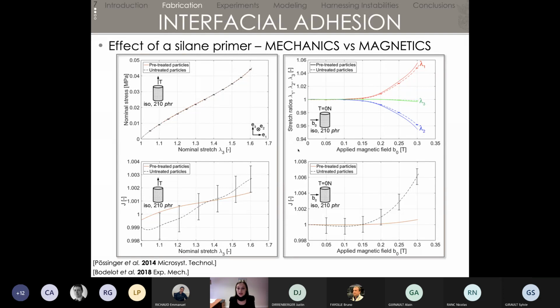And then on the right, the sample which has been pre-treated keeps its J around 1, and the one that has not been pre-treated sees the J going up, which means you have a change of volume, and that is a sign of debonding between your particles and your matrix. And so to elucidate that, Costas did some simulations.